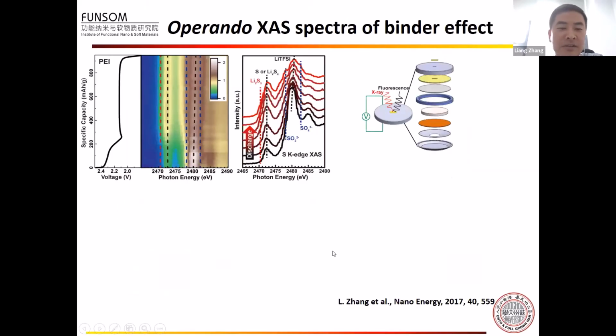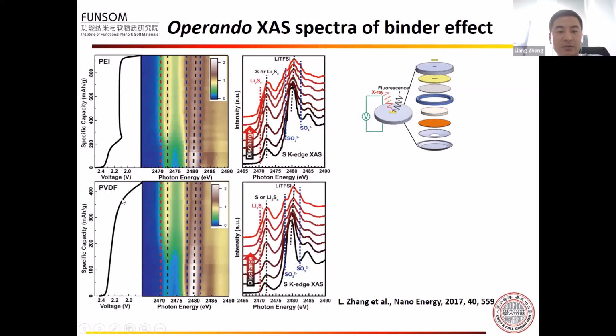To further demonstrate the strong interaction between the PEI binder and the polysulfide, we also perform an in-situ X-ray absorption experiment. Here we use a specifically designed in-situ cell. We can directly detect the sulfur signal in the electrolyte. So the left is a contour plot for the sulfur K-edge results, where the X axis is the photon energy and the Y axis is the state of charge. The different colors indicate different intensity. The right figure shows several typical spectra. For the PVDF results, we can clearly see the increase of the intensity of the polysulfide during the discharge process.